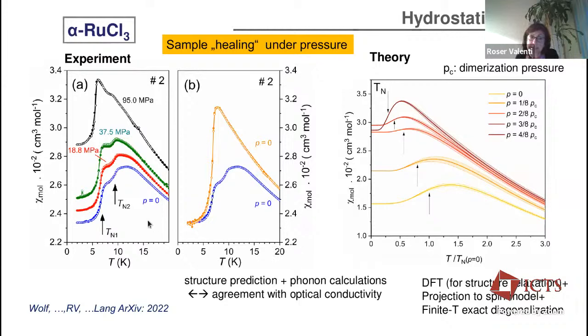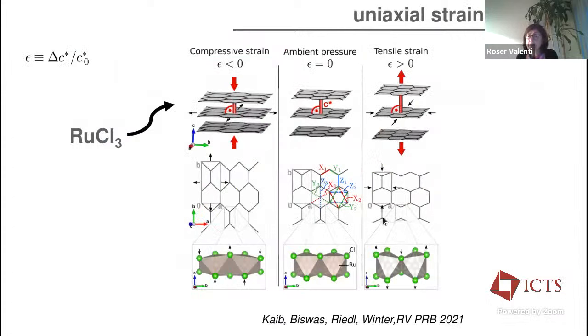So what they find is that by applying these very small pressures, you can, as one says, heal the sample. One problem of these samples is the stacking faults. You can see the presence of stacking faults in that you have, in fact, more than one transition temperature, more than one Néel transition temperature. So they can heal these samples by applying very small pressures, and one can see that also theoretically, as we did with these simulations.